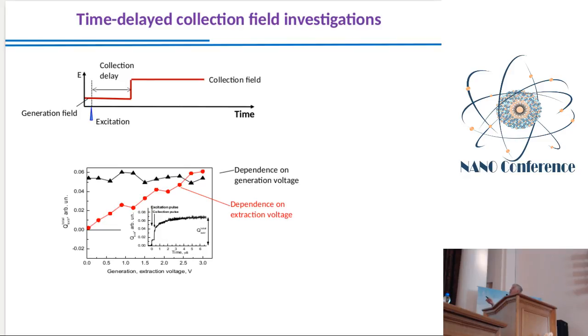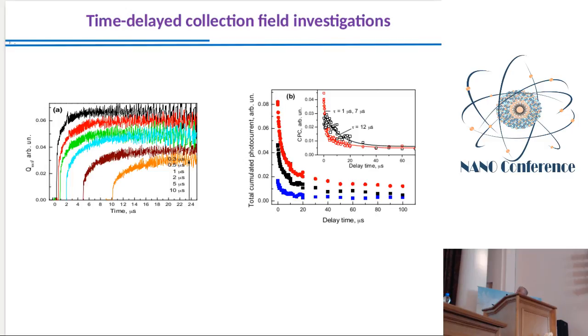When we change the collection delay time, here are the photovoltage transients measured at different delay times. So when the delay time between the excitation pulse and the collection field switching is short, we have strong photocurrent. In fact, here is the collected charge. We collect quite sufficient charge, but when we increase the delay time, the charge collection drops down, and the transients slightly change their shape.